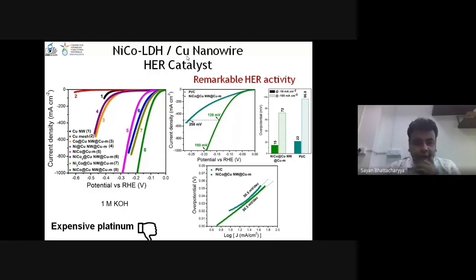And so with this system, what we have achieved is an overpotential which is lower than platinum at 10 milliamp per centimeter square. These are 100, you see. So it beats platinum. So it is a very exclusive result from our lab. And the kinetics of both the reactions, this is called the Tafel slopes. I have no time to tell you about this, but they are more or less constant. And the current density, the amount of the hydrogen which comes out, you see that they are very good.